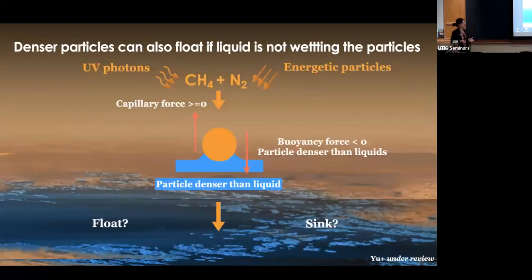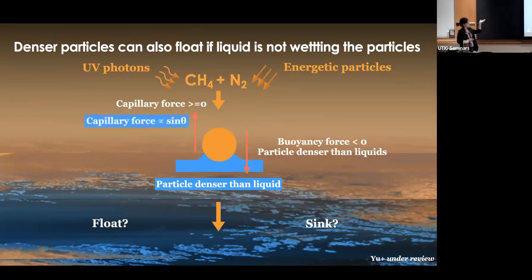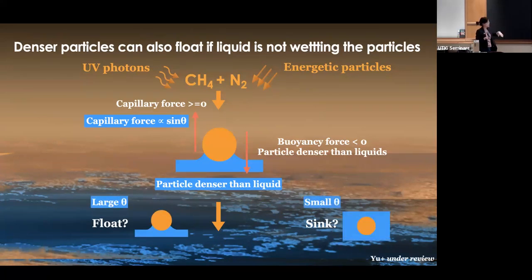Well, we then go on and investigate the other way to make things float, which is through the capillary force, okay? Given that most of these materials are a little bit denser if there are no pores. And capillary force is related to the contact angle between the lake liquid and the solid. The larger the contact angle is, the larger the capillary force you're going to have. So just going there again. But okay, what kind of contact angle are we talking about? The first thing we did is we estimated the threshold contact angle that's needed to make things float, to have enough capillary force to balance the buoyancy.